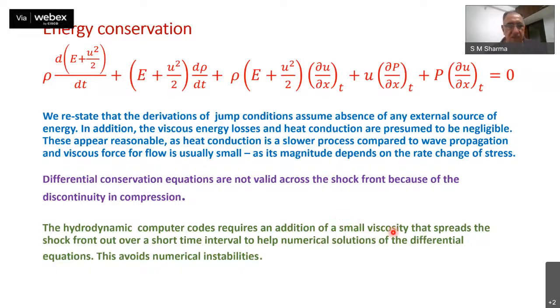That small viscosity actually acts to spread the shock front over a short time interval, so that the discontinuities are avoided in some of those calculations. This is, in fact, the concept of virtual or small viscosity in these equations, which was realized way back when the field started and was introduced by von Neumann in the late or early 40s.